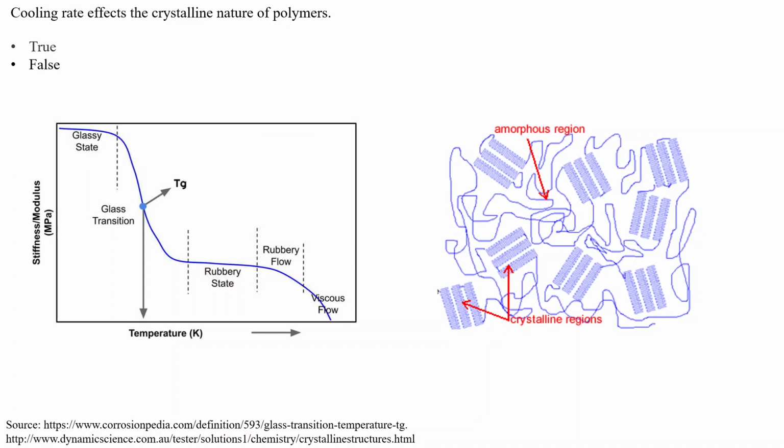So the individual amorphous chains which are present in the open manner like this, when you cool it down suddenly, are restricted in their movement and they don't set back into this crystalline lamella. They are just present in a haphazard manner in this network. You can see that they will be just frozen like that as they cool down. So sudden cooling will just keep the material frozen like this, and the free volume inside the material will be very high. Because of this, the material is extremely brittle, in the sense that it cannot take on any load, it is very inflexible and it will break easily.